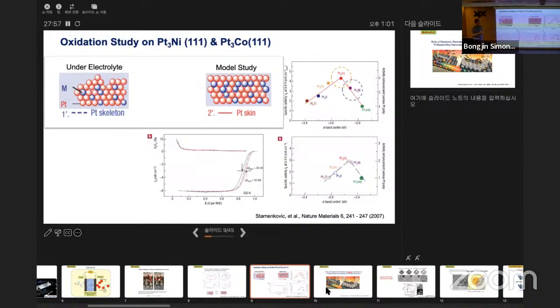It worked really well. But then there were many other cases too. Later he said not only the d-band center, but the d-band width is also important. And some groups came up with many other ideas. So now he's saying this explains the general trend, but not necessarily in all cases; it can be different. In this case, in 2007, the d-band center was hot. We were also collaborating with Norskov, and there was another parallel paper in Angewandte that used basically the same data, but he wrote it in terms of this d-band approach.